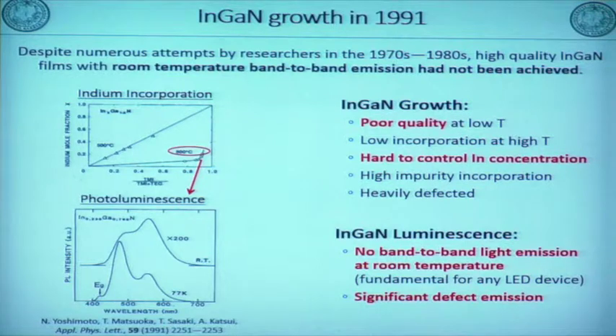Basically, the most active group was Dr. Matsuoka's group. He is now a professor at the University of Sendai, and his group got the best result, but they only observed band-to-band emission at low temperature, at liquid nitrogen temperature. At room temperature, basically no band-to-band emission, basically no emission. So this is the best result, but this material could not be used for the active layer because there is no band-to-band emission at room temperature.